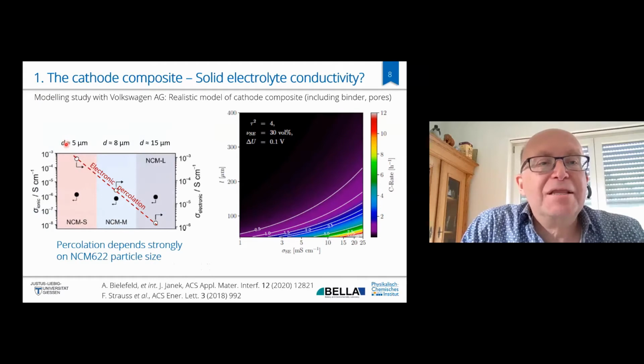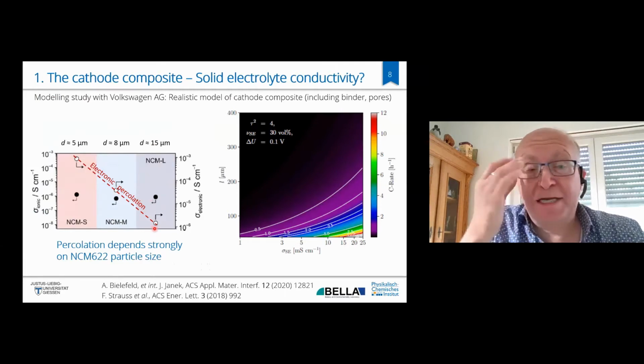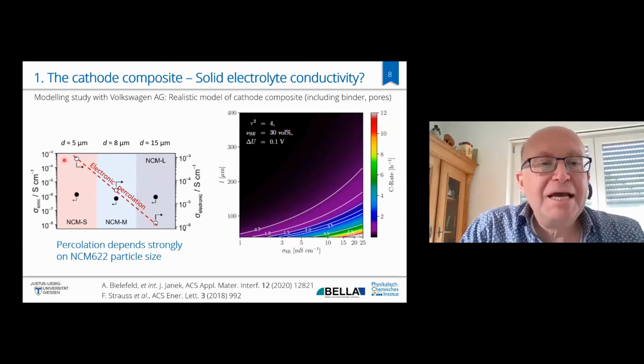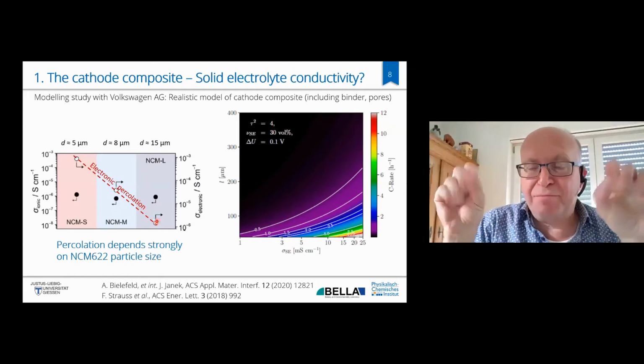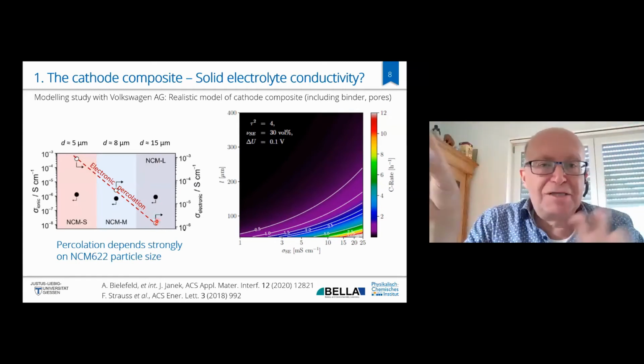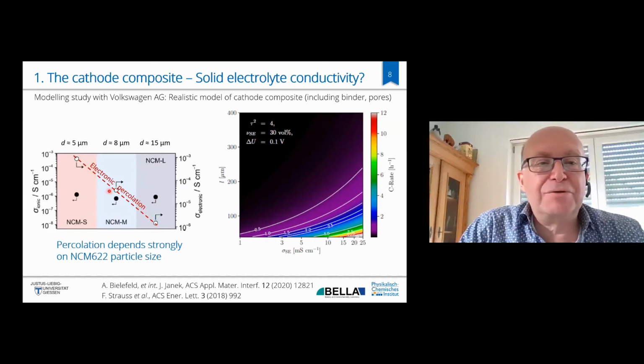So what you see here is that we investigated cathode particles. These are NCM622 cathode particles with different average diameters from 5 to 8 to 15 micrometer. Whereas the ionic percolation is more or less independent of the cathode particle size, the electronic percolation, where no conducting additive is added here, goes down with increasing particle size. So if you have the same amount of cathode material in your cathode composite but with big chunks of cathode particles, then the electronic percolation, of course, goes down. So there is an improvement in electronic percolation going to smaller particles.